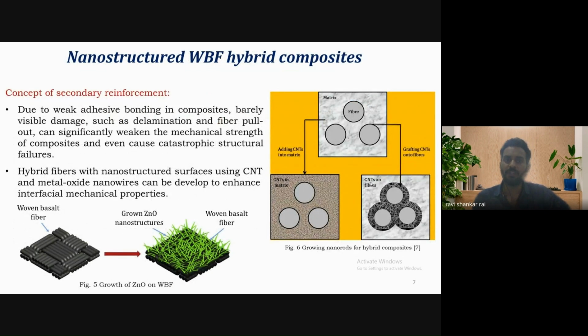So the concept of nanostructured woven basalt fiber reinforced polymer composite is like this. In this image, you can see a simple matrix and fiber. This is just an FRP, you can say fiber reinforced polymer composite. There are two different methods to add the secondary reinforcement. Initially, people add CNT directly into the matrix. They usually add CNT particles inside the polymer matrix. Since the polymer has a high viscosity and we are mixing it with a hand stirrer or similar, the dispersion of CNT into the entire matrix is not completely favorable. So there are chances of agglomeration and non-uniform distribution of the CNT inside the matrix.